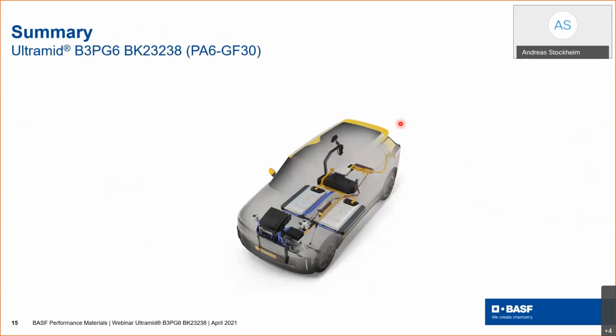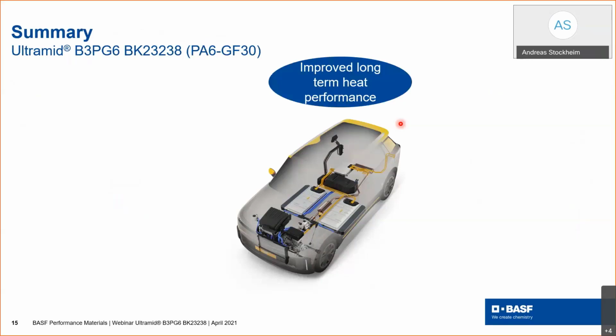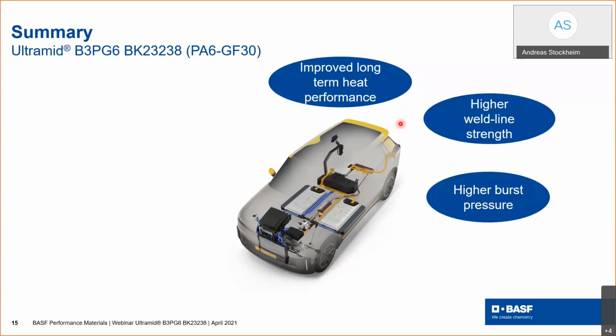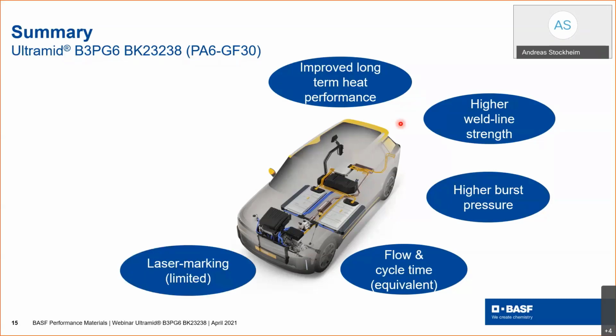In a nutshell, you have seen that there is a strongly improved long-term heat performance on our new B3PG6, as well as a higher weld line strength, wherefore we are also expecting that the burst pressure is even higher on our new product. The flow and cycle time is equivalent to our current PA6 GF30 systems we are offering. And laser marking is possible, but limited. This really depends on the laser our customers are using, and we are currently looking to improve even this laser markability.